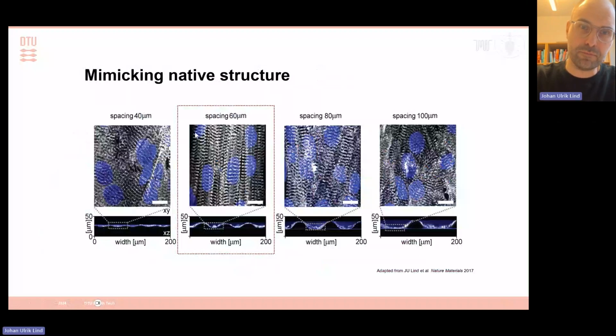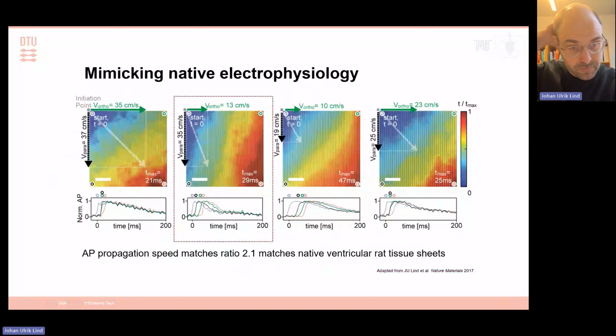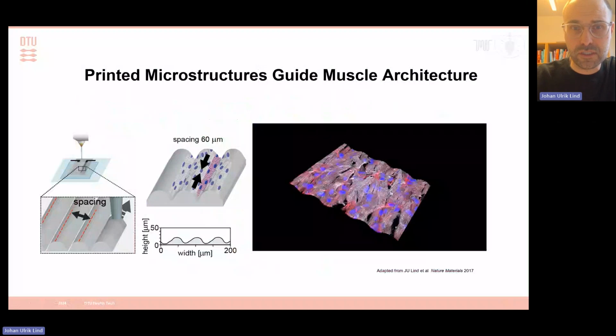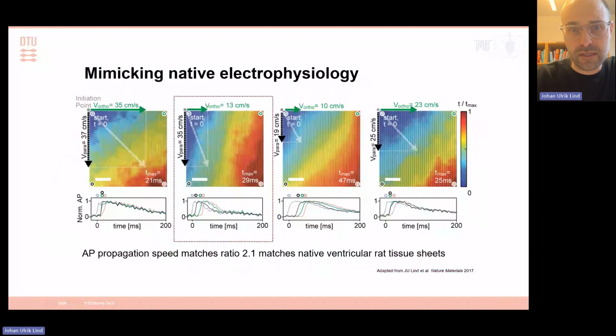Equally important to the contractile units being organized as in the body, you also need electrical coupling. So we studied the electrical coupling of tissues cultured on these groove substrates, and found that in addition to a contractile anisotropy, you also have electrical coupling, so that the electrical signal that is inducing the contraction of the tissue is approximately twice as fast in the long direction as across the grooves, which matches what you see in vivo, or in these ex vivo tissue sheets. So this relatively simple approach, you print some grooves, you seed some cells, is quite efficient in matching native biology. I will return to some applications of this later.